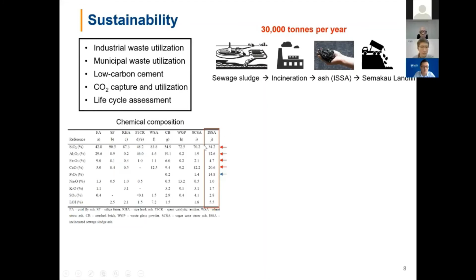Now, if we look at the chemical composition of this sludge ash, we see that it has a high content of silica, a high content of aluminium, and a high content of calcium. And this is very comparable to fly ash, which is already a well-established supplementary cementitious material. That means this incineration ash can potentially be used as a supplementary cementitious material as well, to replace cement.